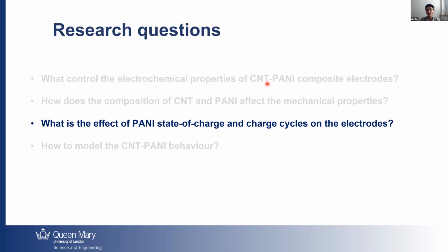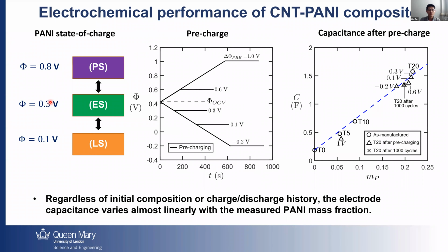What is the effect of PANI state of charge and charge cycles on the electrode? As we mentioned before, depending on the state of charge, like charging the material at different voltages, there are different states for the PANI. So in this test, we use some pre-charge. We charge the electrode at a certain voltage and hold that for a certain time. And then we measure the CV performance and measure the capacitance.